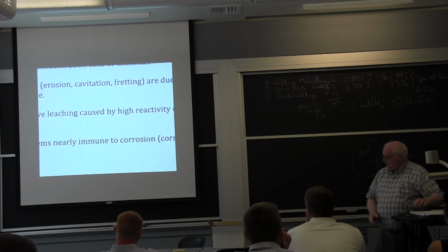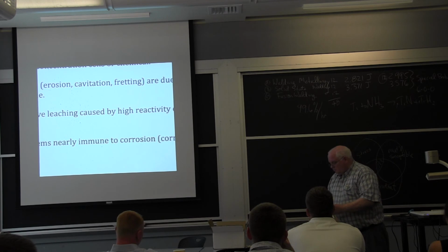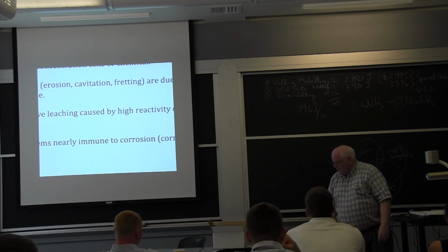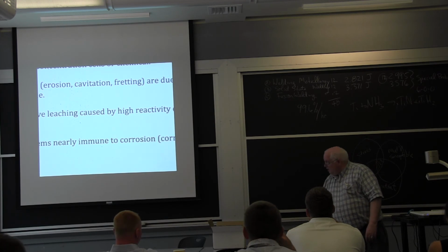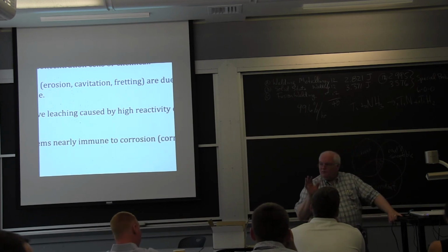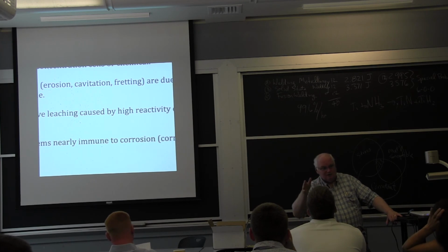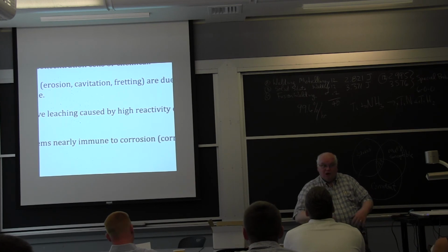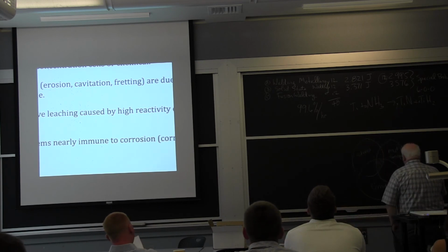But it turns out the spec was to make the parts out of 316 stainless steel, and they made it out of 304, which, we're going to learn, is the garden variety stainless steel. This is the most dramatic case I've ever seen of where you should have used 316 and used 304. So the wrong material can make a big difference, just like I told you about that destroyer going into the Gulf War, where they lost their 3,000 psi steam line because of stress corrosion cracking, because it was the wrong alloy. So these are two stories of using the wrong material.